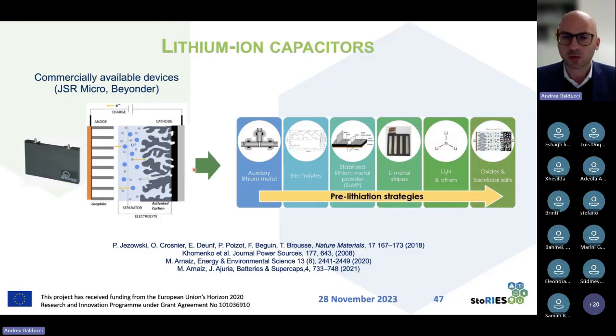What they do industrially to lithiate them is a process called pre-lithiation. So we need to assemble them, and then to bring lithium into the system, one uses auxiliary lithium metal, so that you are putting, for example, a strip or a piece of lithium behind your graphite, and then you are putting the lithium inside. Or you could use the electrolyte, or more recently, different strategies like sacrificial salt or cathode have been used. So this technology is nowadays existing. But there is a problem related to the pre-lithiation process.